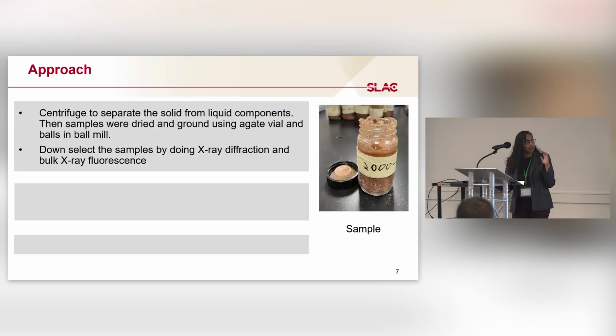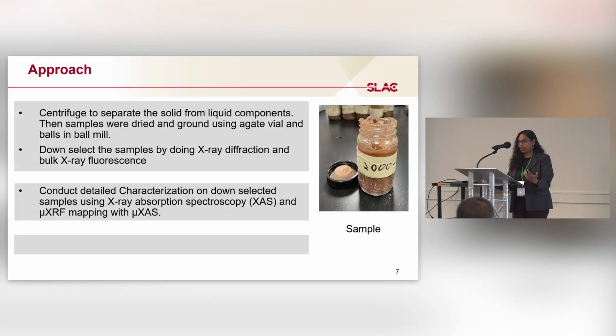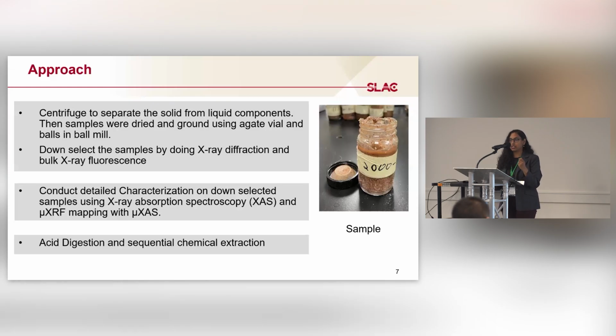And then we did synchrotron analysis, using techniques like X-ray absorption spectroscopy, X-ray fluorescence mapping, and micro-XAS on those samples to identify what species, or what compound, these minerals exist as, so that we can go to the next step, which is sequential chemical extraction, or trying to see how to extract these materials, and finally acid digestion.